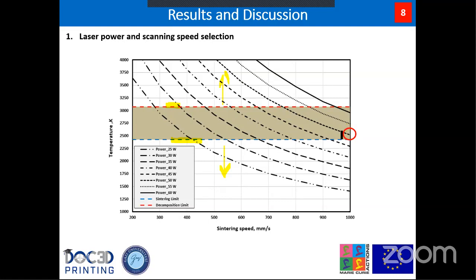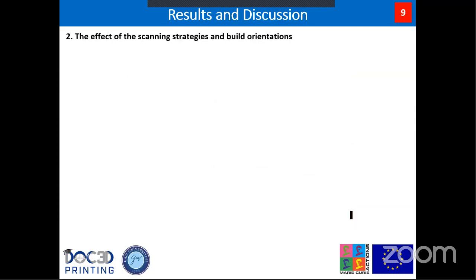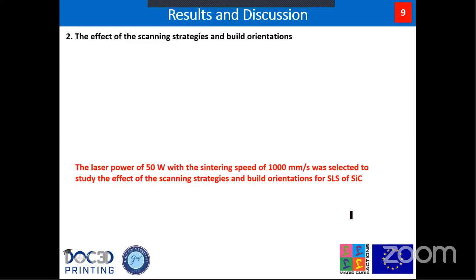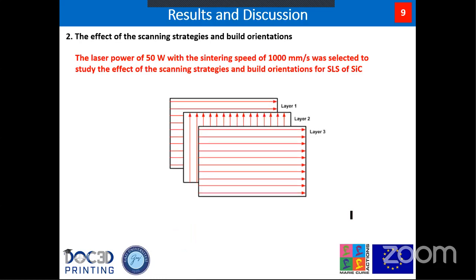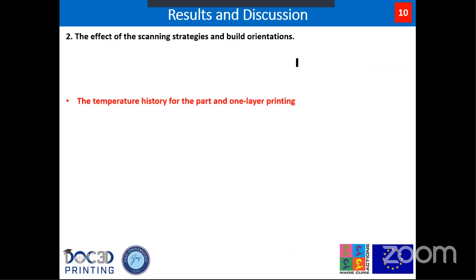In our study, we use a laser power of 50 watt and a scanning speed of 1000 millimeter per second. After that, we studied the effect of the scanning strategy and build orientation, where we used this scanning strategy and build orientation in our study, using 50 watt for laser power and 1000 millimeter per second for scanning speed.